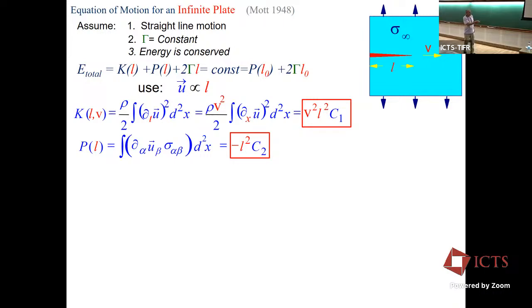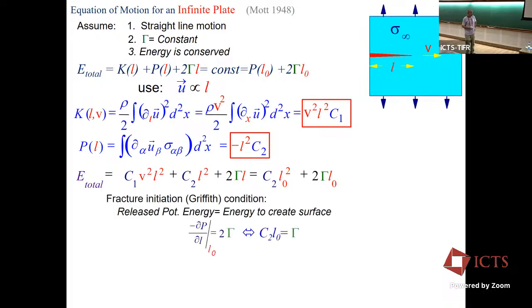So again, the potential energy goes down in the system as the crack advances, and it goes down like L squared times some other constant. The total energy then just becomes this expression by substituting all of this in. And again, the crack initiated at a length L naught. So we just stick in the same constant in this expression for the potential energy. Again, when it started, the kinetic energy was 0.